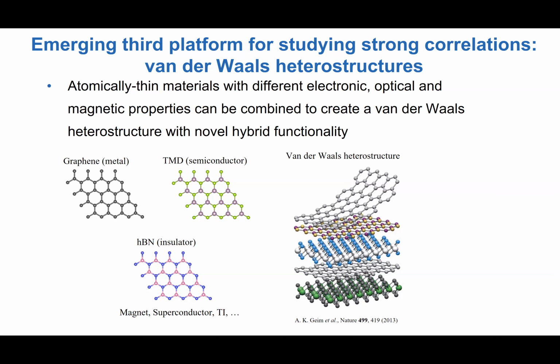So, there are different classes. Again, graphene is a semi-metal. TMDs, transition metal dichalcogenides, are semiconductors. hBN is one of the best insulators one can imagine, with a band gap of about 6 electron volts. And what one can do, as Andre Geim and co-workers have pictorially represented here, is that one can first exfoliate these materials down to the monolayer level, make a library of sorts,